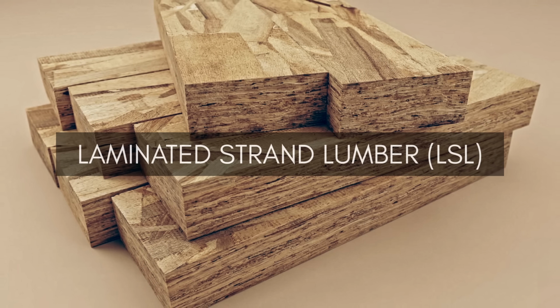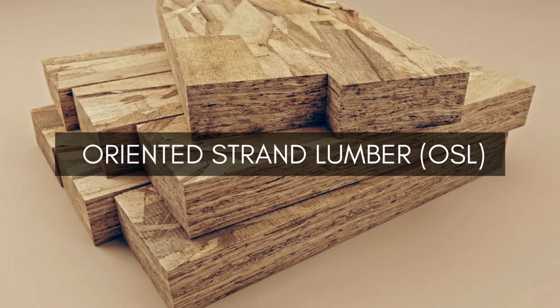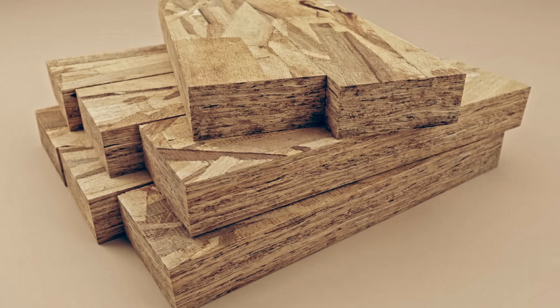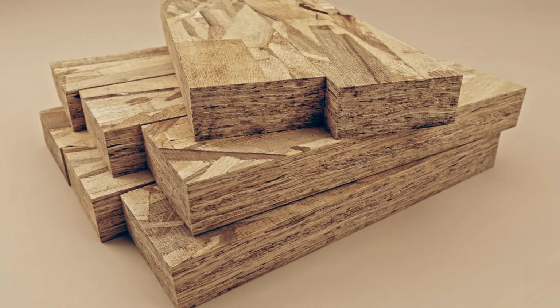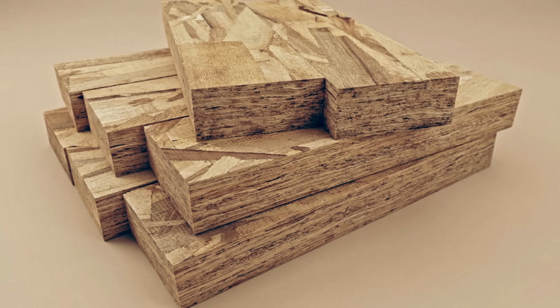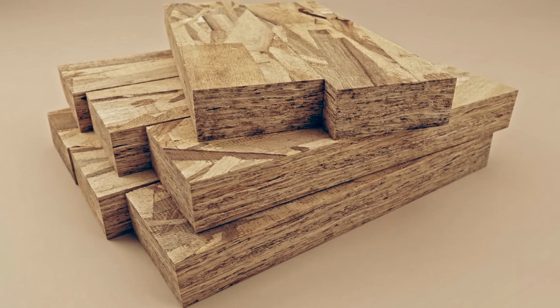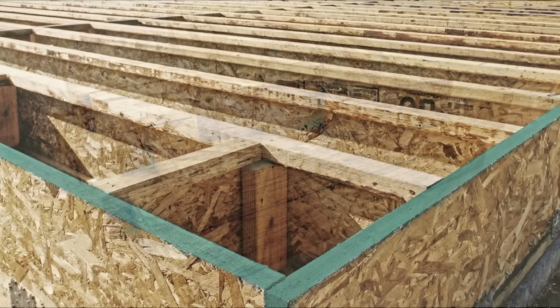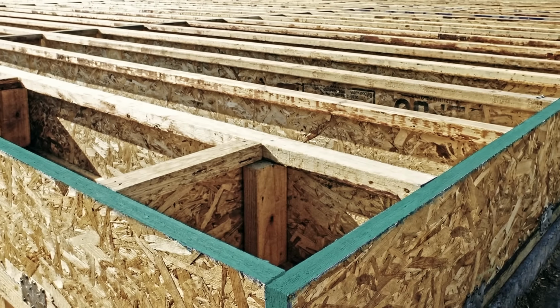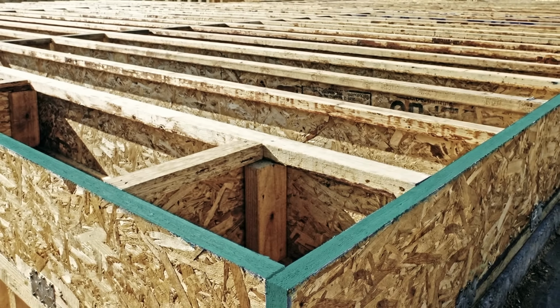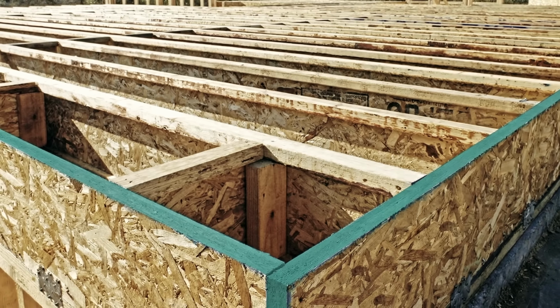Laminated strand lumber, or LSL, and oriented strand lumber, or OSL, utilize flaked wood strands of varying lengths at 150:1 and 75:1 length to thickness ratios, respectively. These are commonly used for rim boards, tall wall studs, and headers where dimensional stability is paramount.